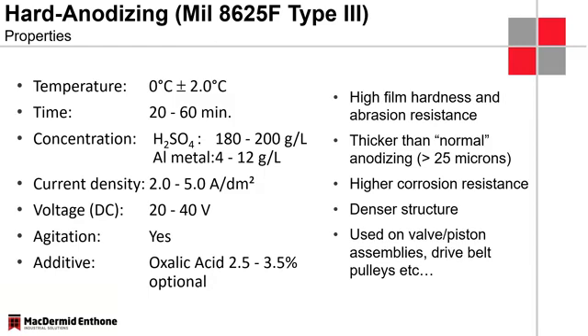So where with the type 2 we reach an equilibrium where we anodize and redissolve the anodizing layer at the same rate, at a temperature of around about 0 degrees, we'll be able to plate a much higher thickness, and that's what we utilize for these hard coatings.